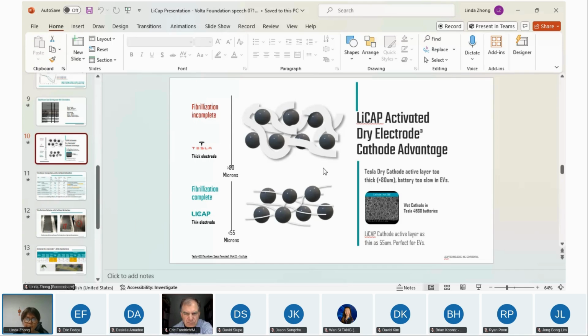The bonding mechanism. So in the older technology, we do not do the activation. So you can stretch the binder to fiber, but the fiber is eventually going to break if you stretch it too long, right? So in the new technology, we activate the binder first. So before they break apart, you can stretch them much longer. And you make the binder much more effective, such that you can reduce the binder by half. So if originally you needed 8% binder, now you only need 4%. If originally you needed 4%, now you only need 2%, right? So now you have less binder, and also your fiber is much thinner. You can make a lot thinner electrode.